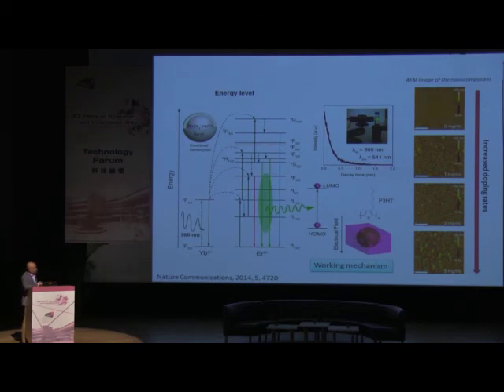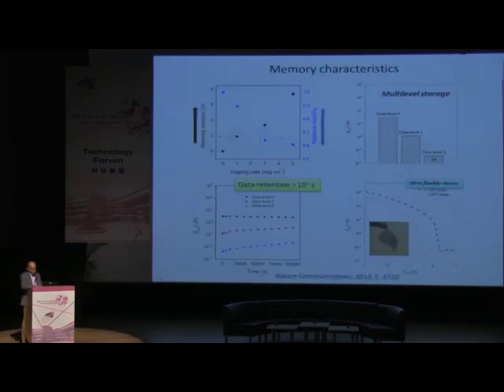This is the AFM micrograph that shows different concentrations of nanocrystals inside. These nanocrystals not only emit light, but also behave like a charge trapping element inside the polymer. When it emits the light, the polymer reabsorbs and creates an exciton, which is an electron-hole pair, and because of the energy barrier you quench, and this particle is again going to trap those charges. Then when you want to release them, use a light to release them. So basically use a light to manipulate whatever you want.